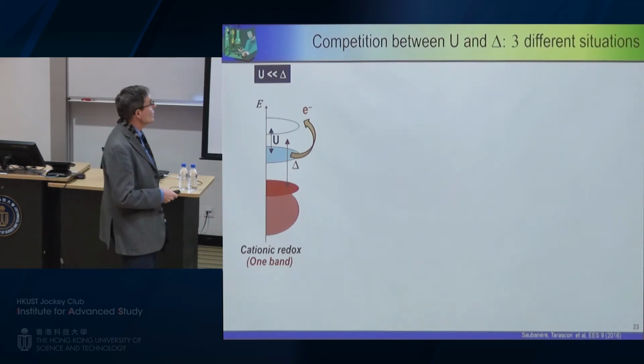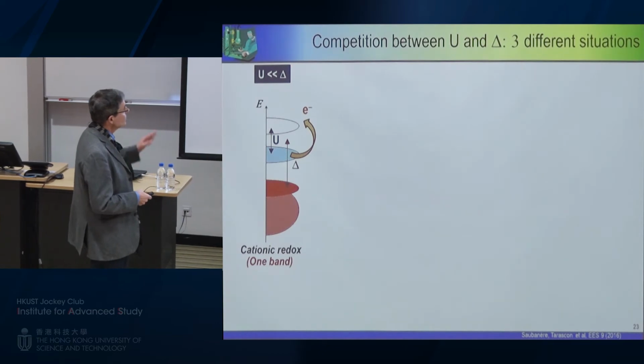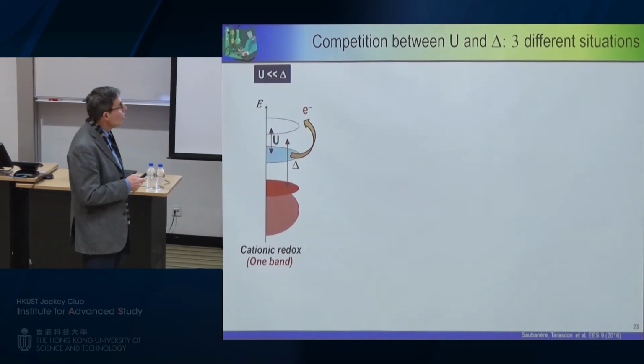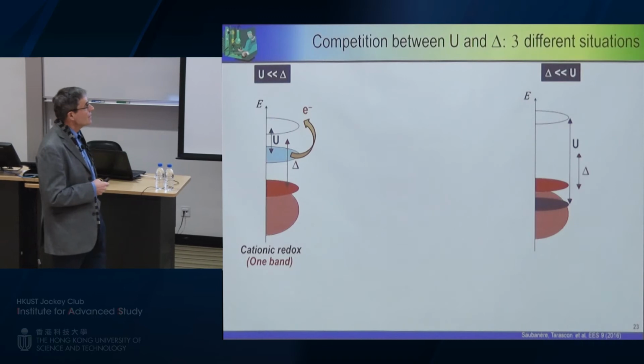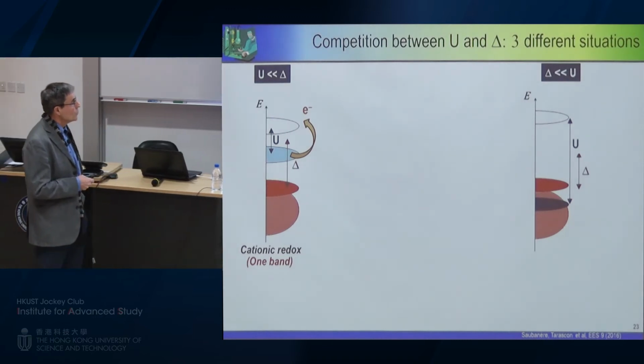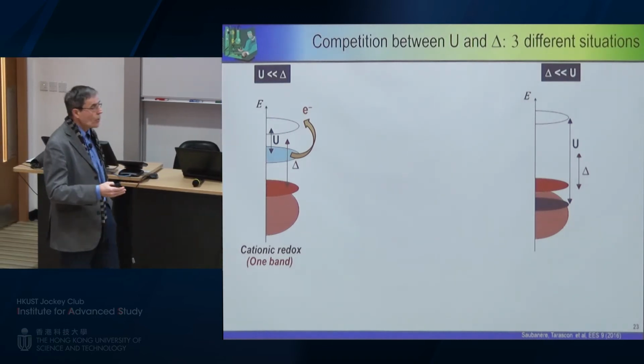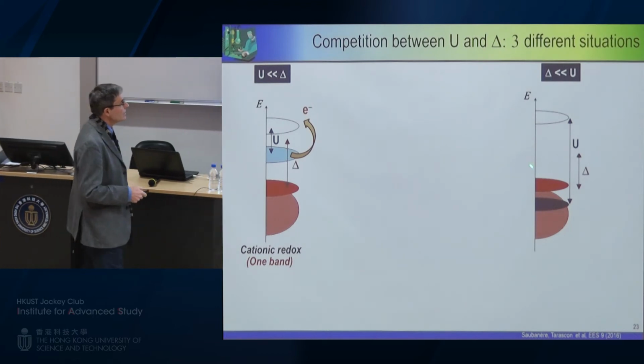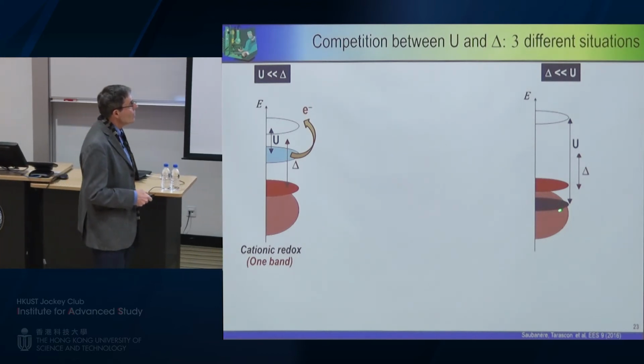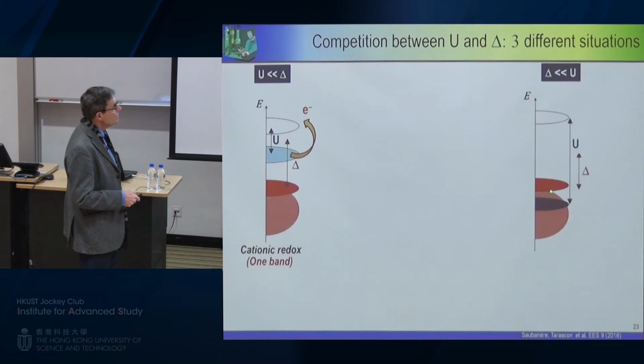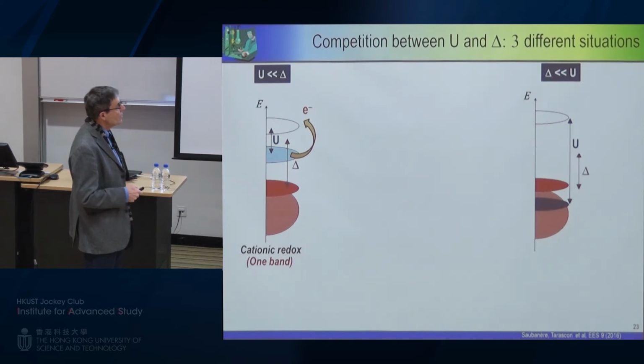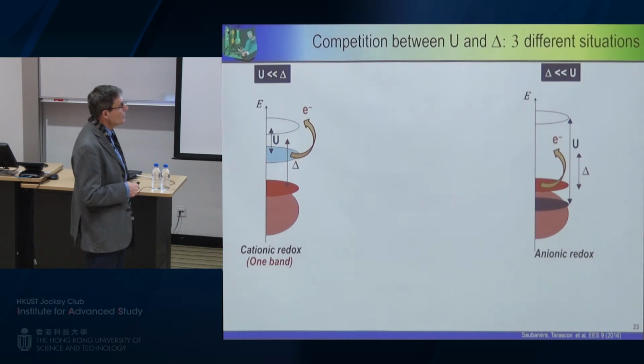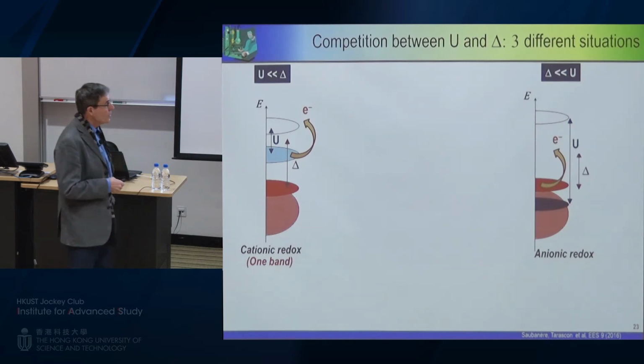I will remove one electron from the anti-bonding state. Now, what happens if I go nearly to the opposite, where delta is quite lower than U, which means in this case we are in a charge transfer regime. You can see here that now the lower Hubbard band is below my non-bonding state. So in this case, I am just removing electrons from the non-bonding state. I am in the case of anionic redox.